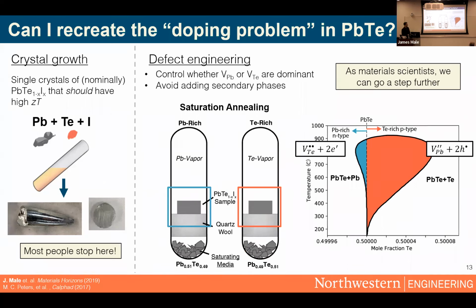that we call saturation annealing. The basic principle is that I took one of my iodine doped pellets and I sealed it in one of these quartz ampules along with some saturating media. And the saturating media contains an excess of lead or tellurium, such that when you reach equilibrium, you essentially have a two-phase system inside this ampule. So your overall composition is in this two-phase region here.